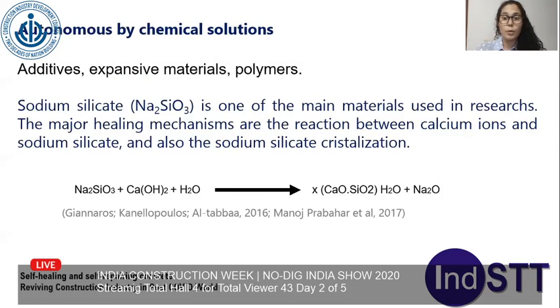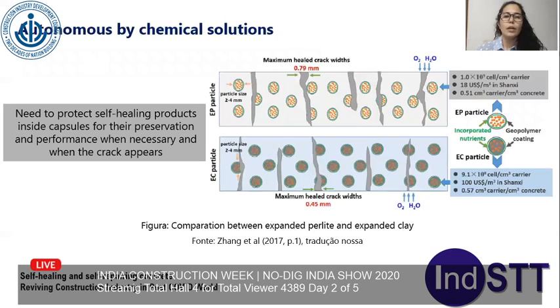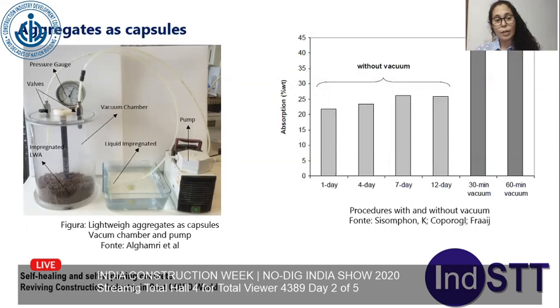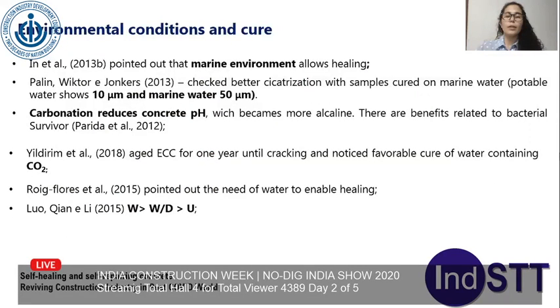We also have the option to use a chemical solution that is usually commercialized ready for use, such as sodium silicate. It also reacts with cement compounds and can also promote the CSH. To use bacterial solutions and chemical solutions, we have the option to use capsules to hold these materials, such as expanded clay or expanded perlite. This study compared those two aggregates, and they discovered that perlite works well for the healing. For example, we also have the option to use or not a vacuum chamber to put the materials inside those capsules.